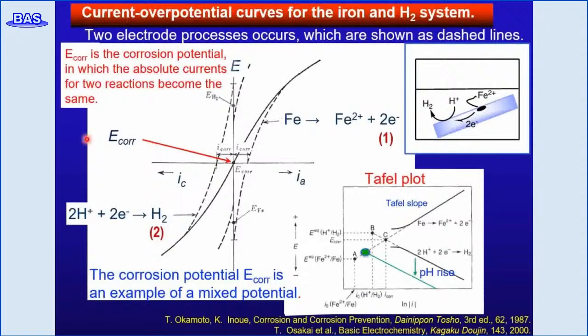Here is the current overpotential curve for the iron and hydrogen system. When iron is corroded by acid in aqueous solutions, anodic corrosion reaction takes place as shown in equation 1. On the other hand, the reduction process in the absence of oxygen is shown in equation 2. The net current, which is measured in polarization study, is the sum of the positive current from metal dissolution and the negative current from the proton reductions. When these two currents sum to zero, this potential corresponds to the corrosion potential.